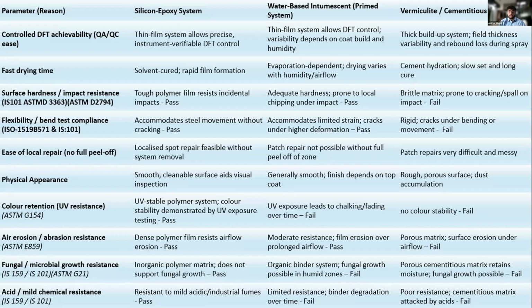Then fungal microbial growth resistance, that is also important in coastal areas. If you can see ASTM G21, that is an inorganic polymer matrix for silicon epoxy, it does not support fungal growth, and in the water-based organic binder system, fungal growth is possible in humid zones, and the vermiculite coating's porous cementitious matrix retains moisture, so fungal growth is possible on the steel. And then lastly, we'll come on to the acid and mild chemical resistance. Silicone epoxy also offers mild chemical and acid resistant properties, while both other coatings do not.